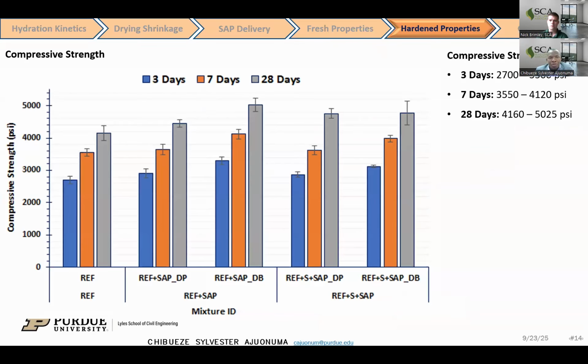And we proceeded with the compressive strength. These are some of the results of the compressive strength that we obtained by the addition of the SAP and directly pouring it or through the dissolvable bag. We can see that there was a steady increase in the compressive strength, because we tested the compressive strength for 3, 7, and 28 days. And then we see a steady increase in the compressive strength with age. And then also we had comparable results between the addition of SAP directly and that of the dissolvable bag. The same was true with 30% cement replacement using slag.